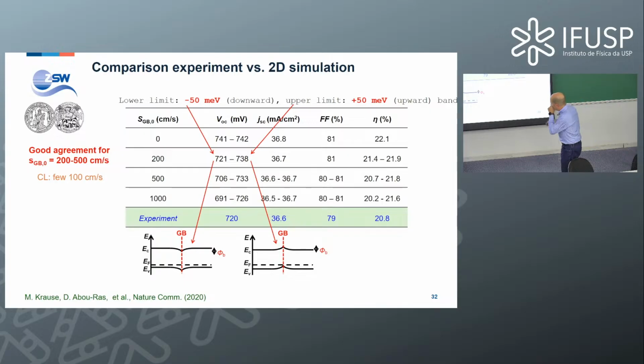What you can see is what I already told you, because the band bending values are so small, the current is hardly affected. It remains almost the same. There's hardly any effect on the transport. But there's a strong impact on the open circuit voltage, right? And it fits to what we actually predicted. It's a few tens of milli-electron volts, yes, when you assume a certain recombination velocity range. In this case here, there's a good agreement with what we find here. And in these measurements of CL, we find a median value of a few hundred centimeters per second that agree very well with the order of magnitude that we can estimate here.